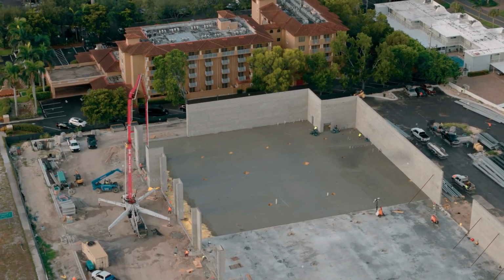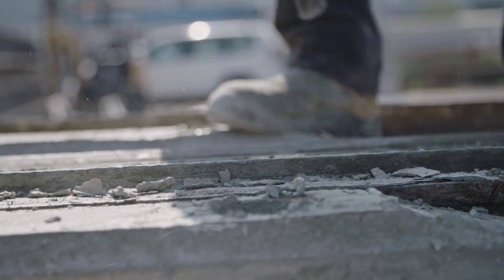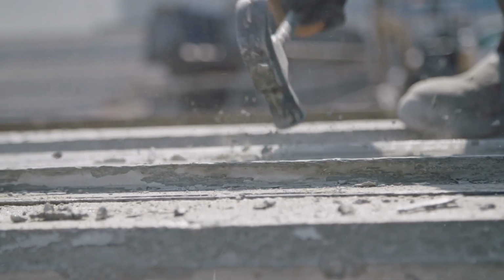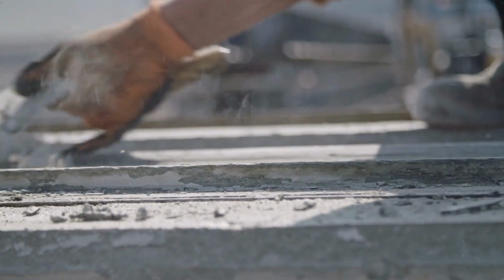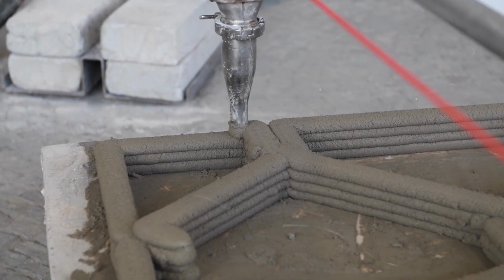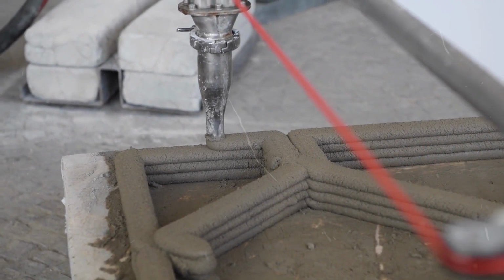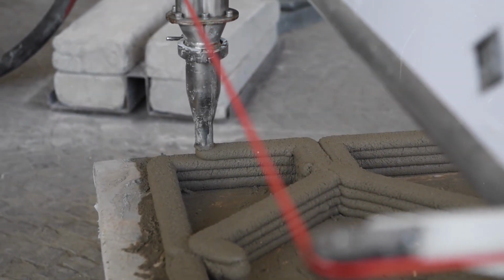Cracks start at voids, because voids are stress concentrations where the material is locally weaker than its surroundings. Water infiltrates through voids, and with water comes the dissolved salts and chemicals that destroy concrete from the inside. In coastal environments and anywhere roads are salted in winter, those chemicals travel through the voids until they reach the steel reinforcement bars buried inside the concrete, where they trigger corrosion that can silently destroy a structure's structural integrity over decades before anyone sees a crack on the surface.